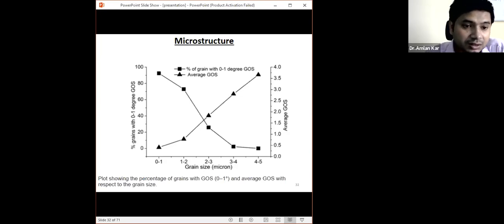But for the coarse grains, which have not been completely recrystallized, we can see 4 to 5 microns is the maximum grain size where the GOS values are very, very high. So that means it is subjected to deformations. This is the continuous deformation process, and the bigger grains are subjected to shear deformations, and because of the shear deformations, they actually get fragmented. They convert to smaller grain size because of continuous dynamic recrystallization, and because of the grain rotations as well as evolution of the